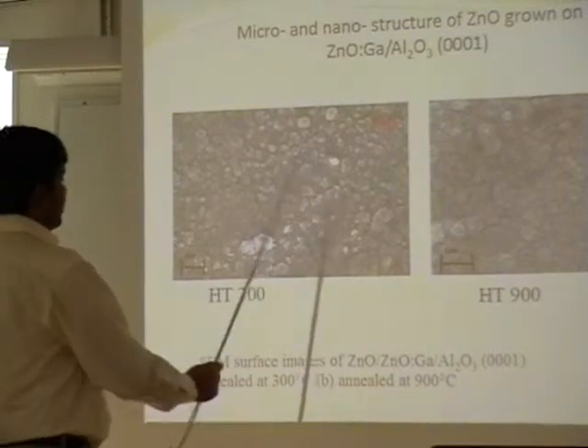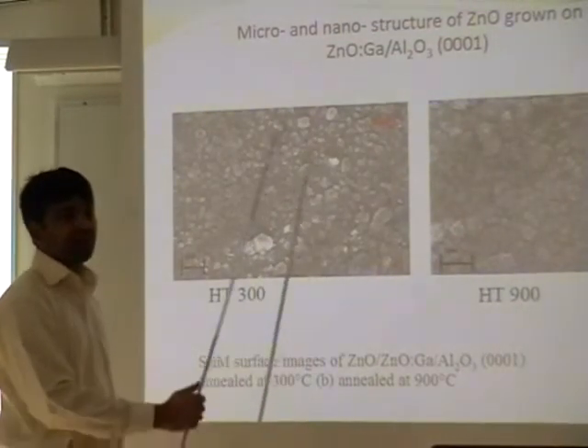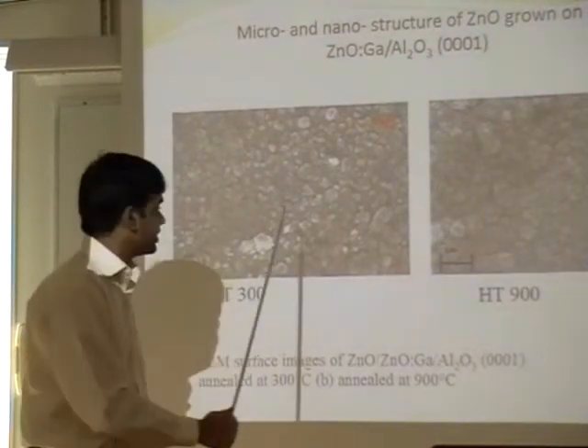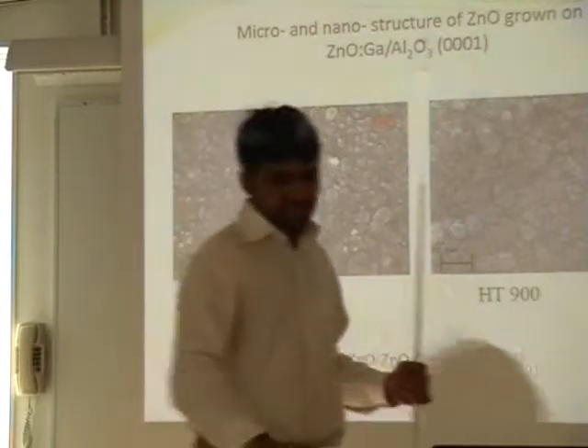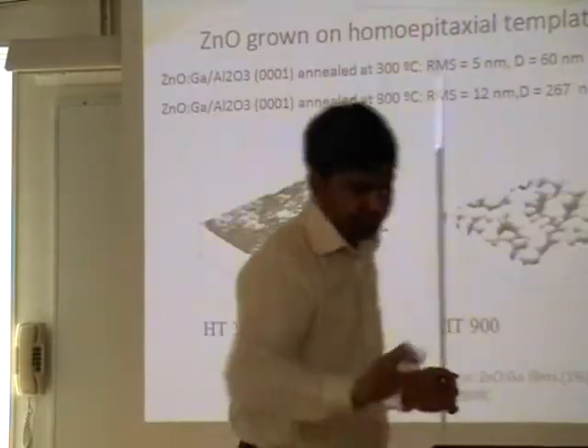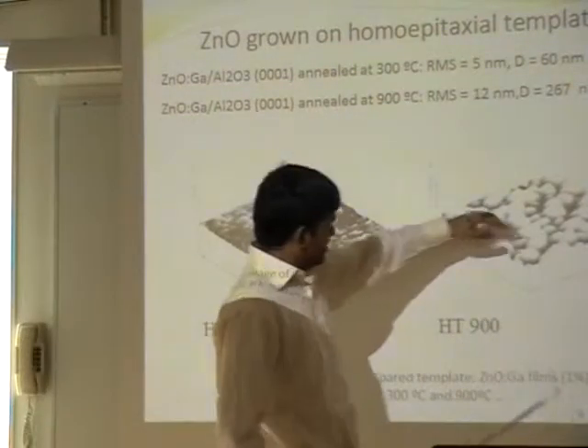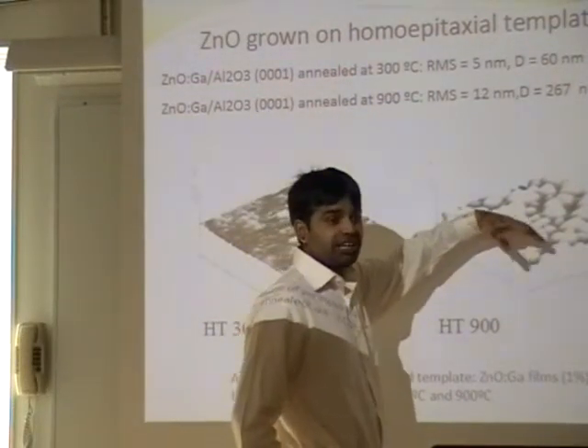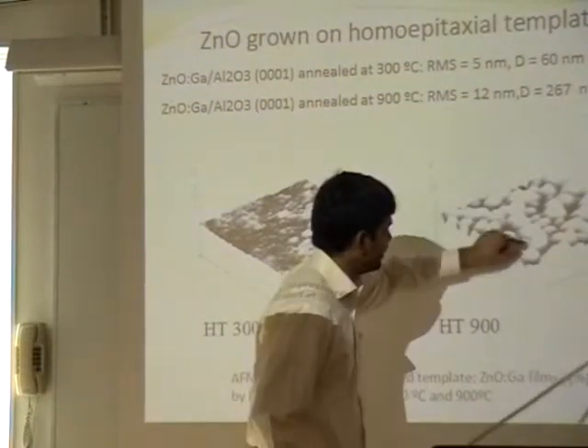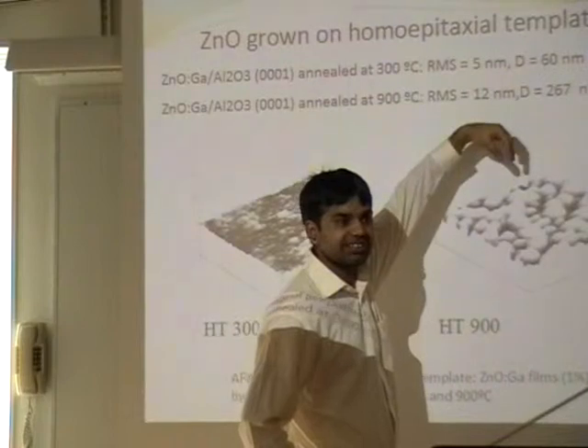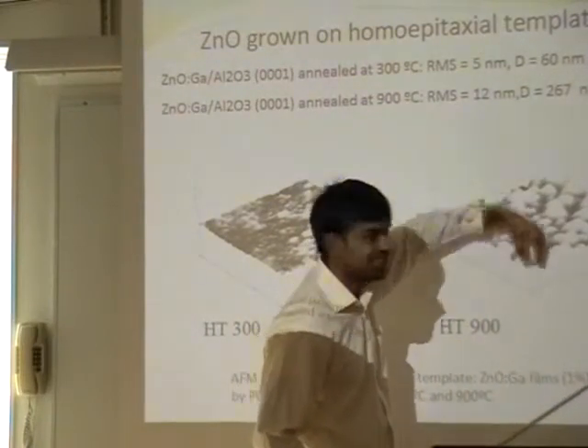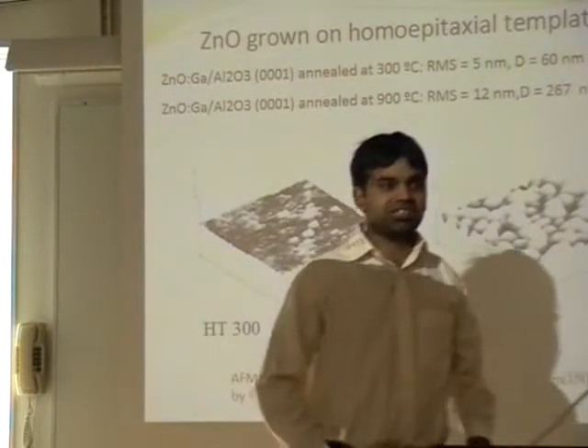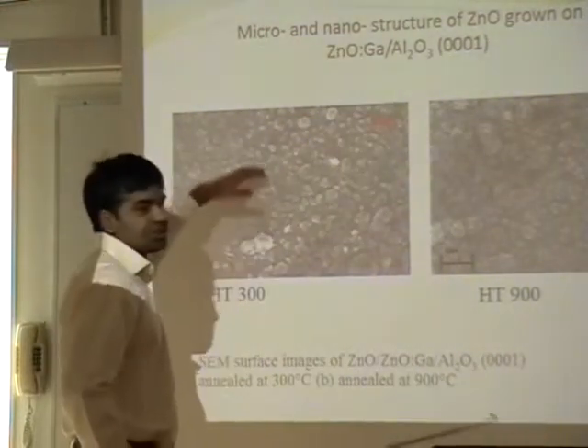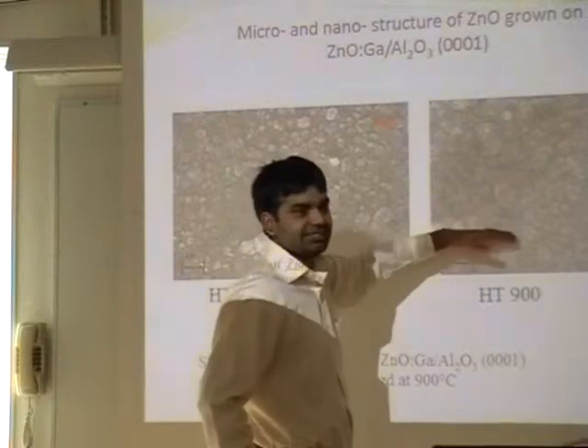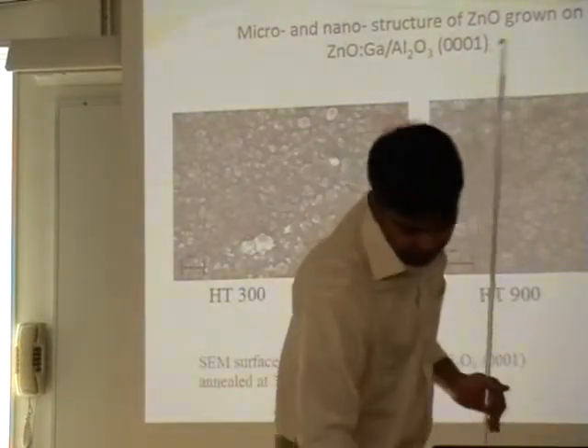Here all the samples through SEM figures, annealing and then after growth of zinc oxide, you can see. Actually our idea was that after annealing we will grow the zinc oxide again, then the grain size becomes bigger. Our idea was that they would look like nano pillars, but unfortunately we couldn't get such a result. The grains became more suppressed, and you can see through the optical property.